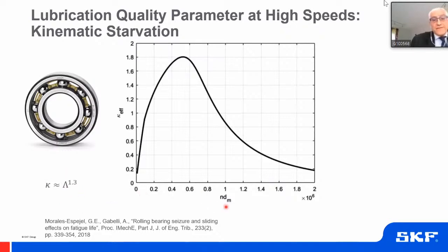And here you have the speed, basically the multiplication of the RPMs by the mean diameter of the bearing in millimeters, and that gives you a measure of the speed. So we know that when we increase the speed, the film thickness will increase until a certain point, but then starvation will take control, and it will actually reduce the film thickness if you keep increasing the speed.